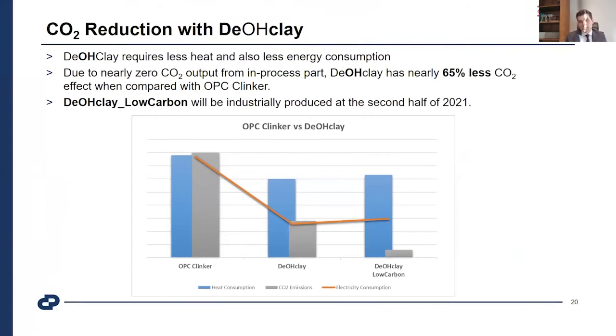When we look at the CO2 reduction with DOH clay compared with OPC, you can see from the graph at the bottom left the standard OPC clinker. The blue columns are the heat consumption to produce that product, and the gray ones are the CO2 emissions while producing that product. The orange trend shows the electricity consumption per ton of that product. As you can see, compared with OPC clinker, nearly 23% less heat consumption is used to produce 1 ton of DOH clay.